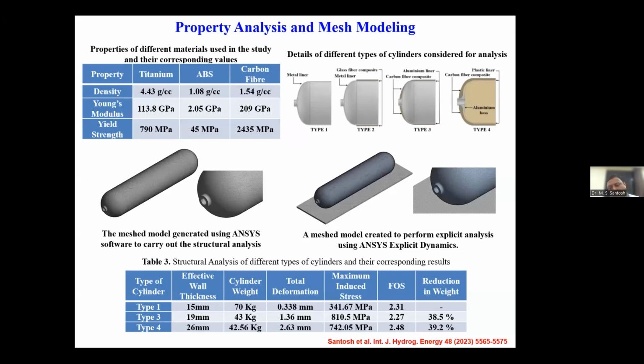When you look at the weight reductions as well, there is a significant amount of weight reduction from type 1 to type 4. In type 3 also, there is 38.5%, whereas in type 4, the kind of material that we use matters a lot. And subsequently, 39.2%, or nearly 40%, reduction in weight compared to type 1 is quite evident. This makes the cylinder comparatively lighter and easily transportable.